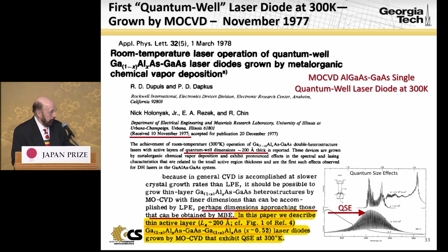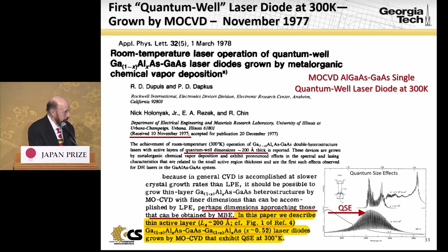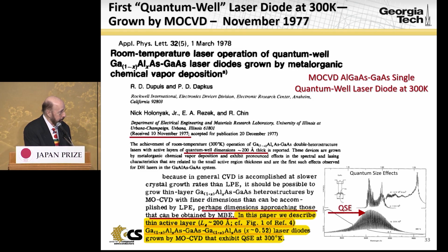So here are our results from that work, published in March of '78 but submitted, as you see, in November '77, showing room temperature operation of quantum well lasers. These devices had a single quantum well, so the entire gain region was just one quantum well, unlike the 40 or 20 pair quantum well lasers reported earlier. And you can see very strong quantum size effects because the emission shifts from around gallium arsenide to higher energy and higher quantum states as we move to higher energy.